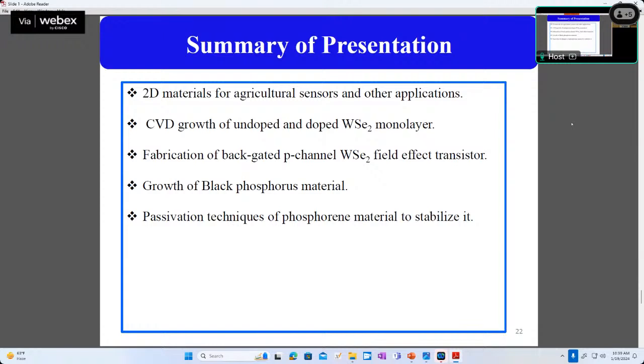So this was about a few growth techniques which we use to fabricate 2D materials, and we have seen how these materials can be suitable for different sensor fabrications. Okay, and we have seen how using a CVD system we can perform these growths, and a P-channel WSe2 FET, how we fabricated that, and growth of black phosphorus material. Okay, and passivation techniques also we have seen, how to stabilize a material if it is unstable in atmosphere.